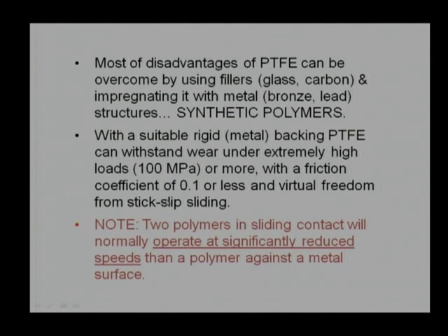Well, in the case of PTFE, they show the same static coefficient of friction and almost the same kinetic coefficient of friction, there is no variation. That is why we say that it is almost free from the stick-slip phenomenon. That is why PTFE can be utilized. Of course, PTFE alone cannot be utilized, it needs to be mixed with some fillers and needs some support, so that thermal conductivity is increased and the ability to resist compressive force increases.